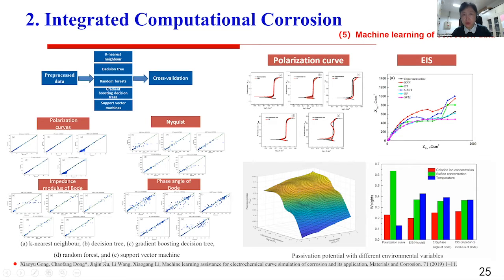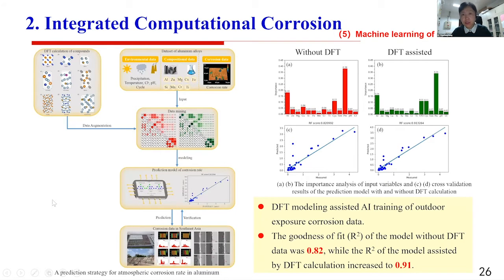This is about using different methods, like k-nearest neighbor and decision trees. We tried to analyze different kinds of polarization curves and also EIS data. After that, we chose the random forest as the best one to do the estimation. And this part is about the recent work we just carried out. This is published result. This one, we just want to use the DFT modeling assistant with AI training for the outdoor exposure corrosion data.